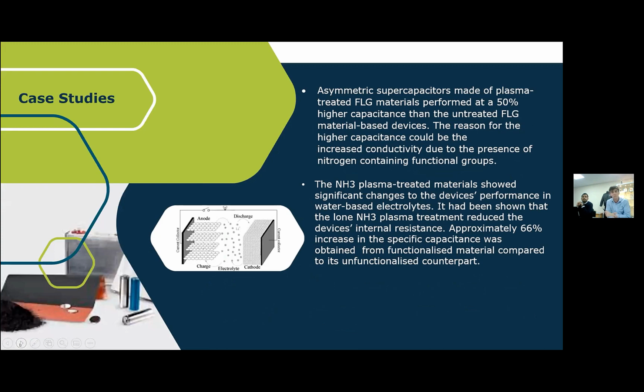Some other case studies are based on supercapacitors. So we developed some asymmetric supercapacitors made of our plasma-treated FLGs, which are few layer graphene, and they performed outstandingly well, with around 50% higher capacitance than untreated FLGs. The reason for that is better electrical performance that we obtain from nitrogen-containing functional groups that are beneficial for this sort of enhancement. Finally, we have ammonia-treated graphene materials, which are suitable for supercapacitors based on water-based electrolytes.